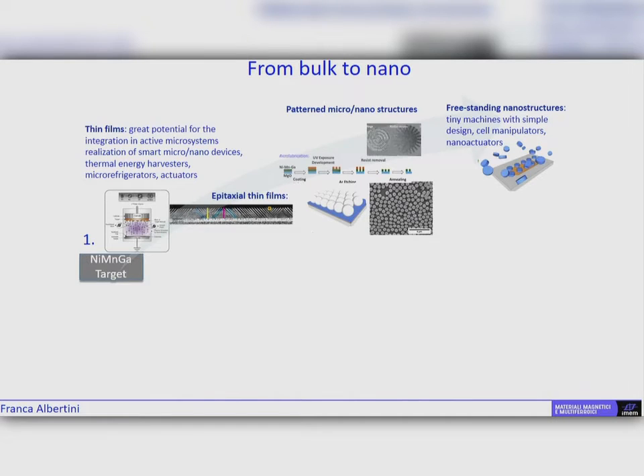Going to our work of today, starting from bulk material, and after selecting a good composition, we have studied thin films that have a great potential for the integration in active microsystems, and also for the realization of micro-nano devices that could be energy harvesters, micro-refrigerators, or actuators. And we have produced epitaxial thin films of different thickness and on different substrates. Then we have moved to patterned micro and nanostructures, that is still an almost unexplored field. And from that, we have also detached this patterned material from the substrate in order to obtain freestanding materials that are materials with a simple design,